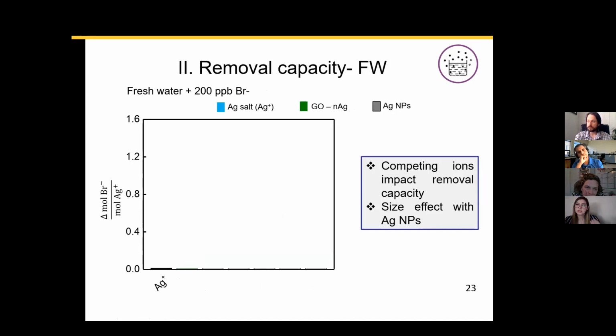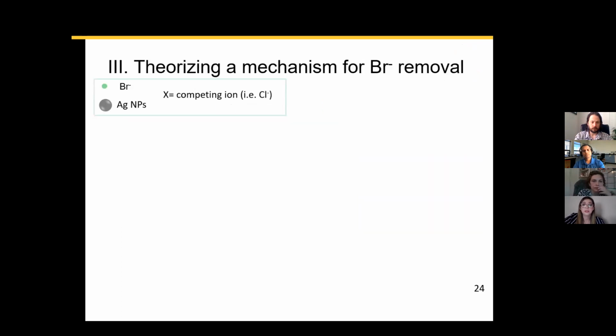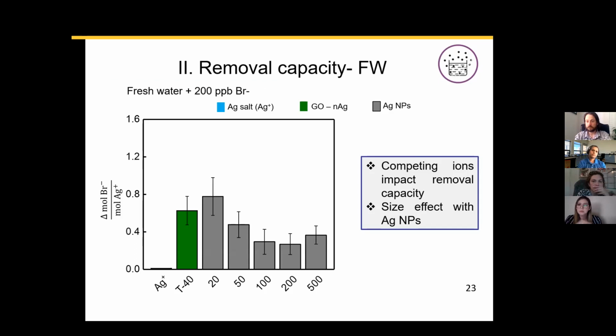Now, we wanted to go a little bit further, and we wanted to see if competing ions, as we increase the water chemistry complexity, have an impact on the bromide removal capacity. And we do see that, in fact, if you look at the silver salt, that great removal capacity that we had in model waters is completely hindered by the presence of competing ions. We did this in a synthetic fresh water system, where we know that we have chloride and sulfates, which will also interact very strongly with silver, and therefore reduce the ability to form these silver bromide complexes. When we look at our nanocomposite, we see that the removal efficiency is actually very high, and it's significantly higher, especially compared to the silver salt alone. And when we look at our silver nanoparticles, we see that the removal efficiency is also keeping that high effect. And we also see that there is a size effect with silver nanoparticles as well.